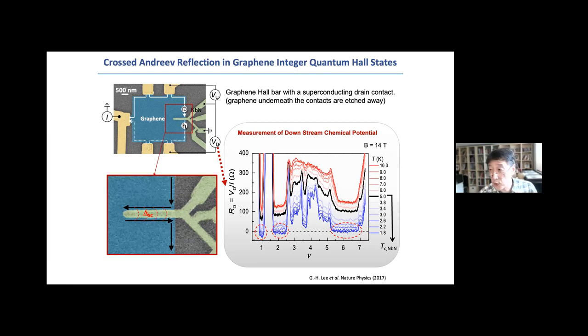Now, one idea for viewing this cross-Andreev reflection is using the concepts of Majorana physics or the semiconducting nanowire type of idea. When we make the contact, we basically remove the graphene underneath and backfill with the superconductor, right? For a moment, if there is no superconductor, the quantum Hall edge state will just follow through the trench we created like this. Now, the presence of the superconductor basically couples these two counter-propagating quantum Hall edges, in terms of spatial direction, through the superconductor. This has a very similar flavor to how one can create Majorana states, Majorana zero modes, in semiconducting wires in very similar formats. So one can view this type of cross-Andreev reflection combined with a very thin superconducting contact as a kind of analog of forming Majorana zero modes in semiconducting nanowires with proximitized superconductivity, right?